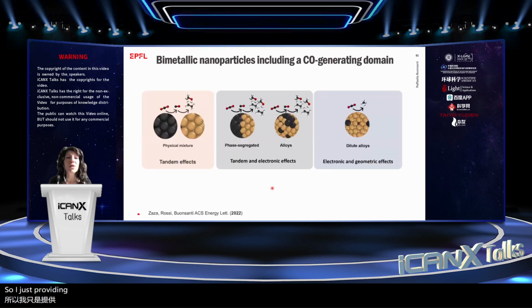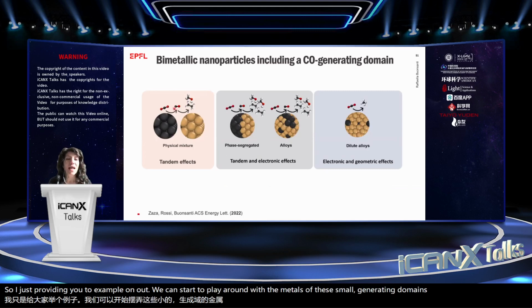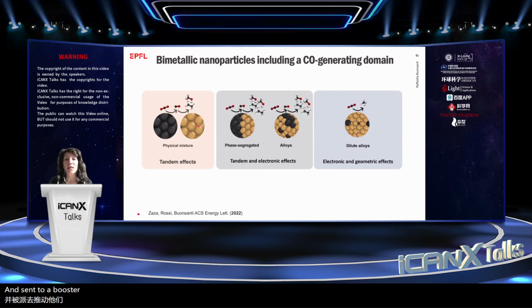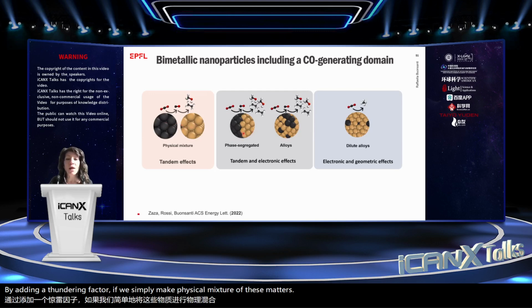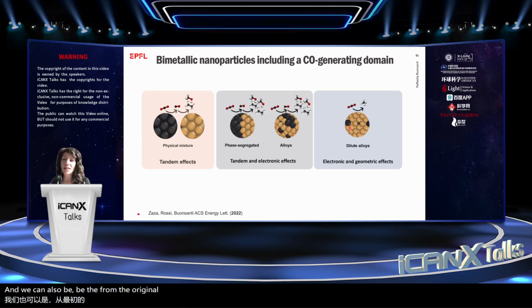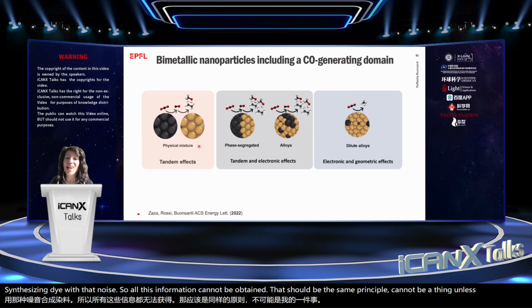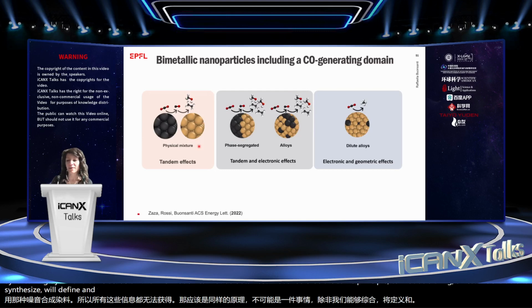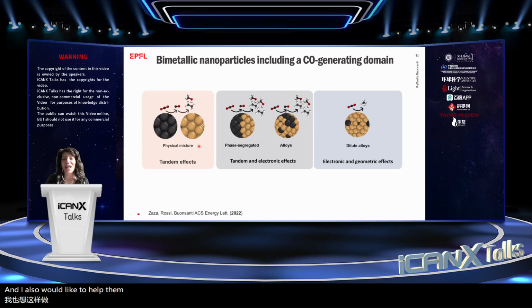So I just provided you 2 examples on how we can start to play around with the metals of these CO generating domains and start to boost the C2 product compared to pure copper by having a tandem effect if we simply make a physical mixture of these metals, or we can start to boost them even further if we combine tandem and electronic effects. And we can also deviate from the original selectivity if we start synthesizing dilute alloys. So this design principle cannot be obtained unless we are able to synthesize well-defined and tunable materials.